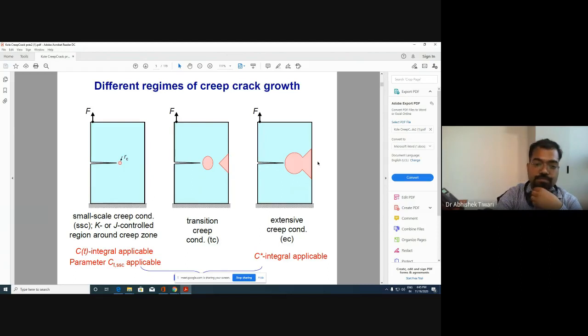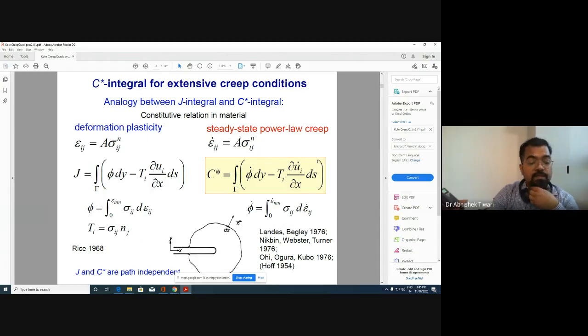So if you remember, we discussed the J integral in the elastic plastic deformation once we have a crack. What was happening in the J integral is that we assumed that the material is deforming non-linear elastically, which is also called deformation plasticity. The name does not suggest anything about non-linear elasticity, but the assumption in deformation plasticity is that unloading or non-proportional loading is not allowed. So you are simply monotonically increasing the load. You are not allowed to decrease the load. And that kind of plasticity is called deformation plasticity.